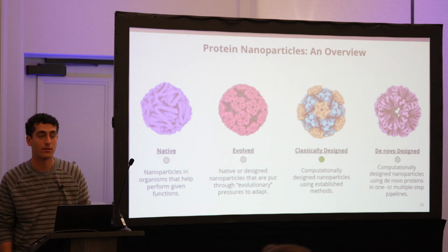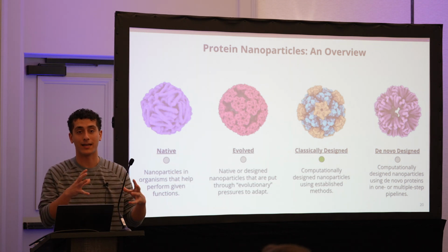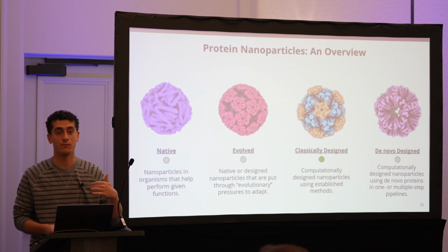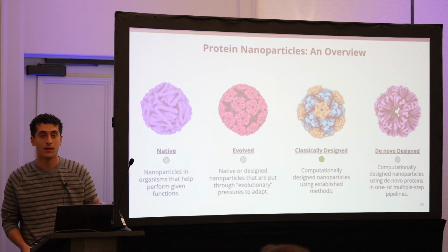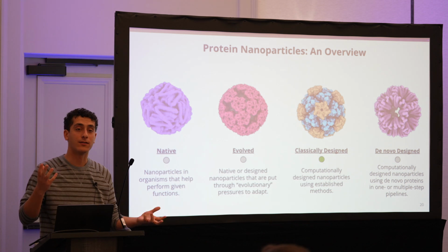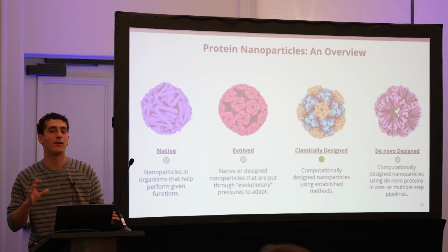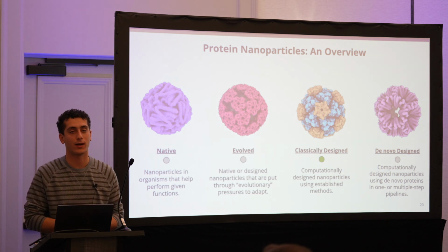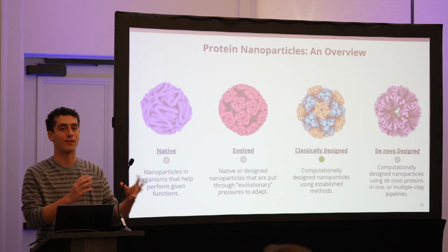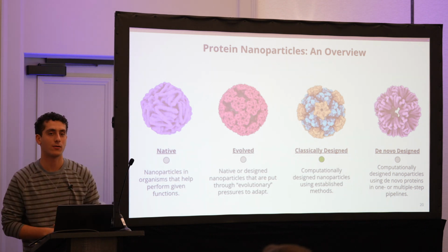So that's one example. Another thing people are looking at is drug delivery. If you wanted to package something inside of a nanoparticle and deliver it, you can, in theory, do that as well. We've designed pH-sensitive nanoparticles that fall apart in the endosome as the pH changes. So there are definitely a lot of potential applications, but you're right, it's very hard to design these robustly, and then to actually get them to the cells they need to go to is where the field is going, but we're not quite there yet.